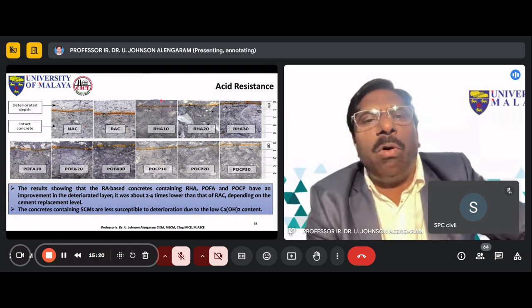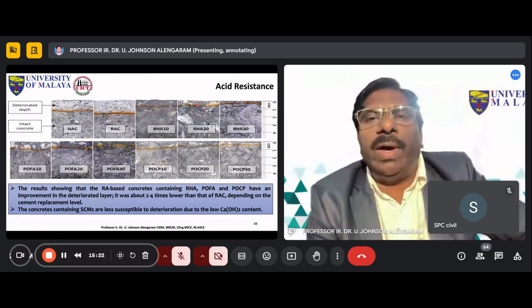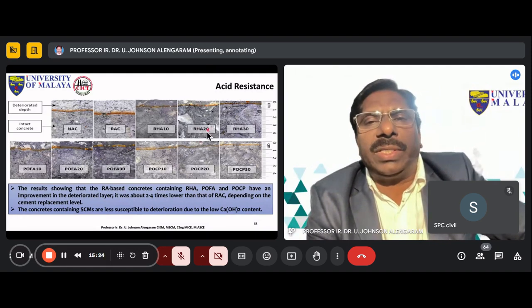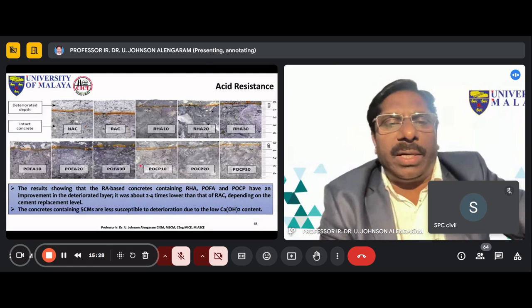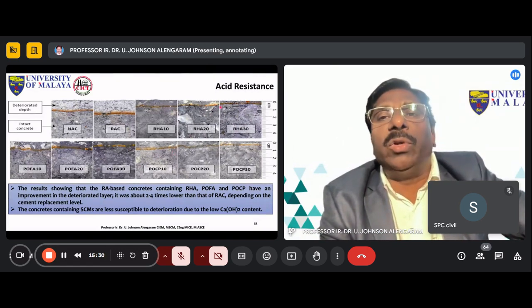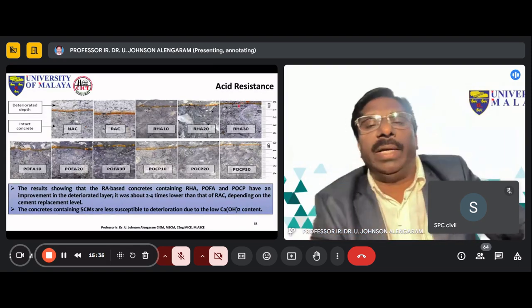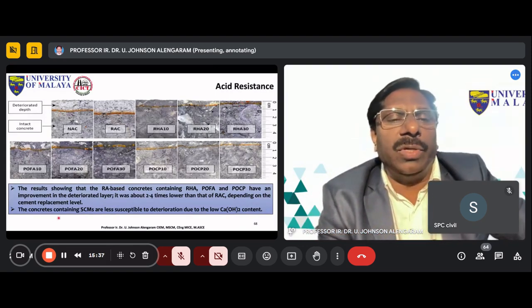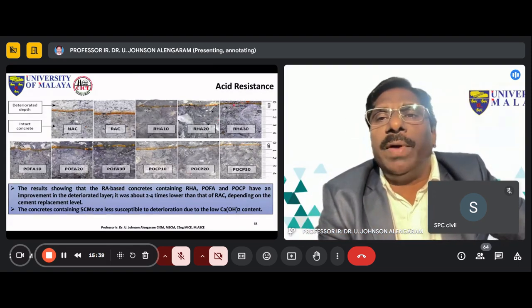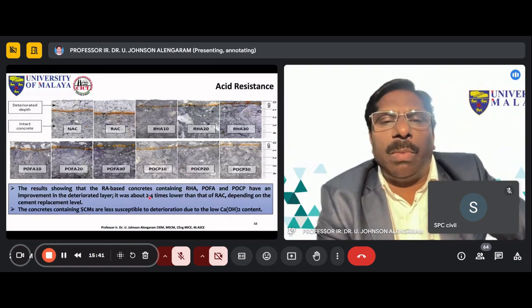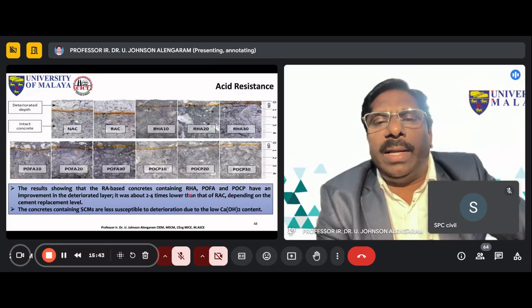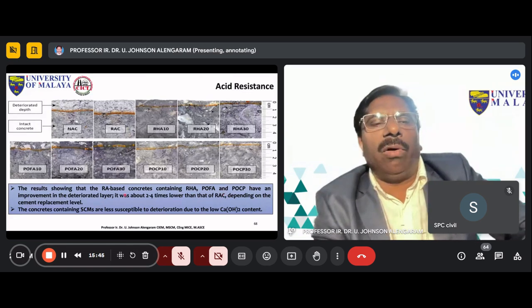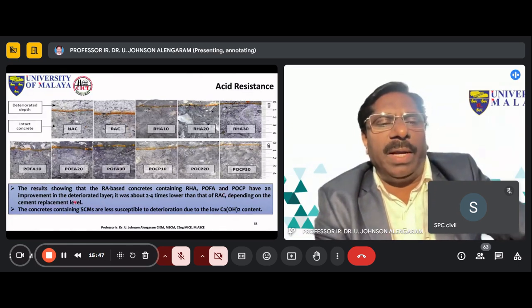You see that this one has more layer deteriorated, whereas when we add rice husk ash 20% or rice husk ash 30%, the durability increased, whereas the deteriorated layer decreased. So that shows the durability is increased, or the durability is good. The deteriorated layer has lower depth here. It was about 2 to 4 times better than the recycled aggregate concrete, depending on the replacement level.